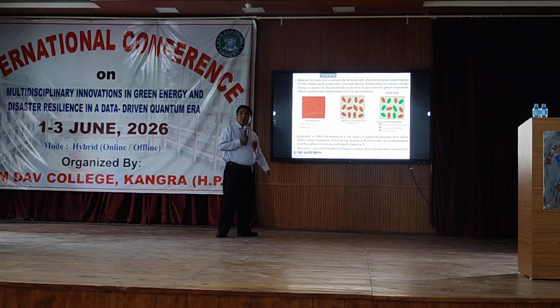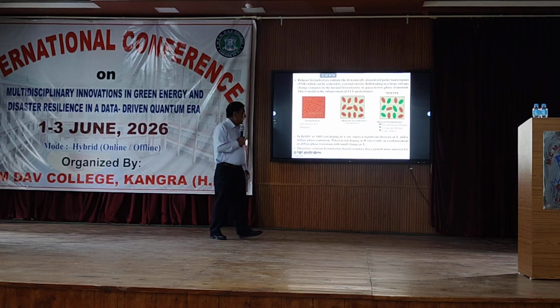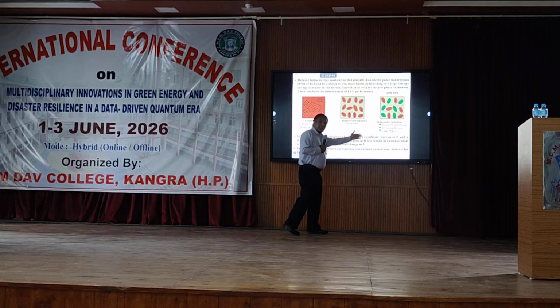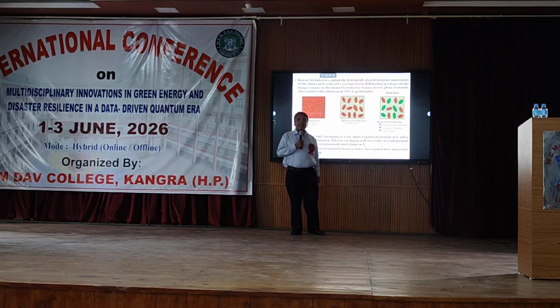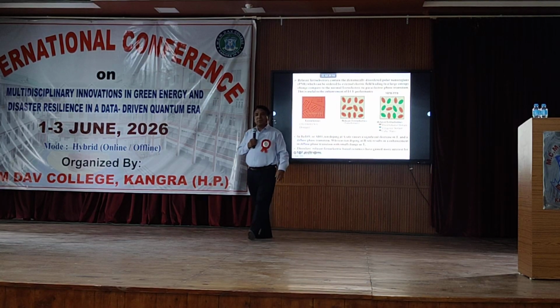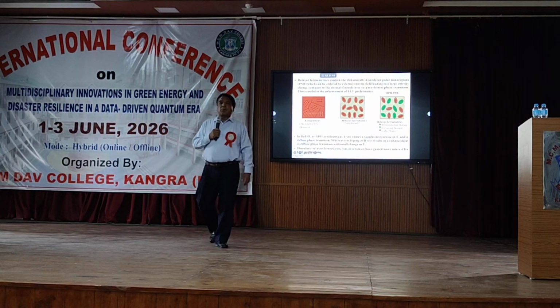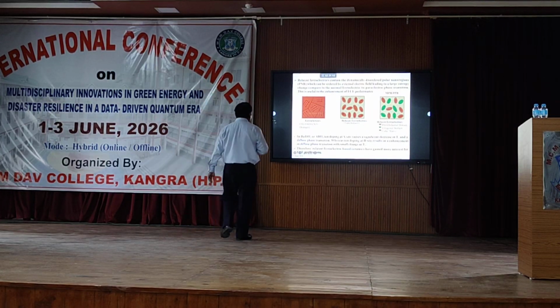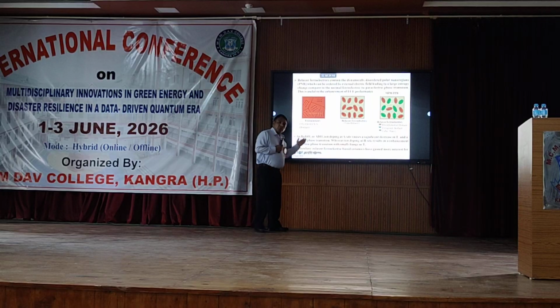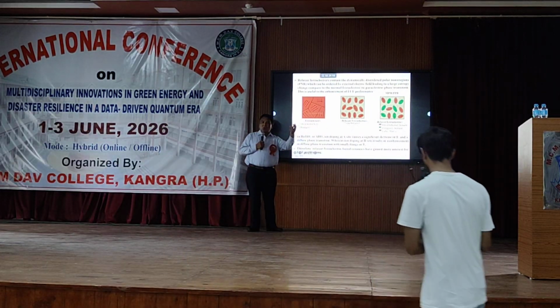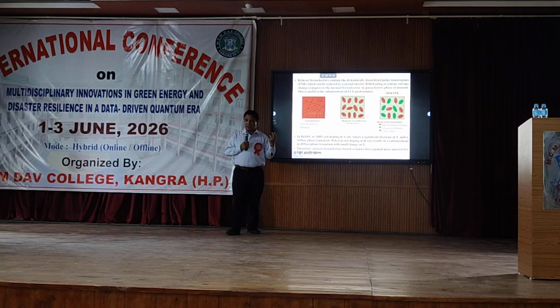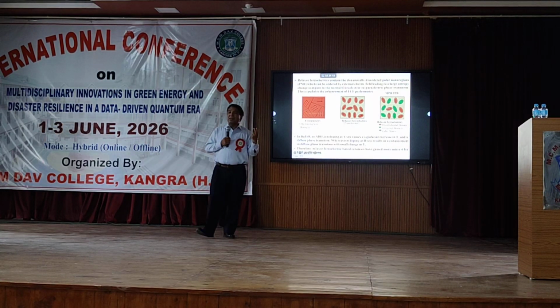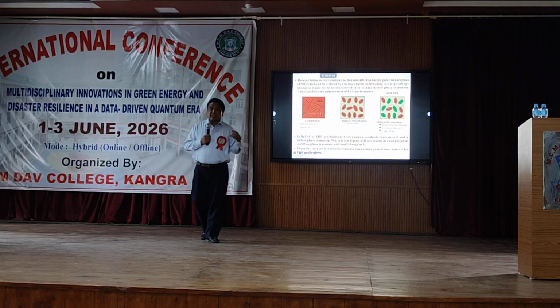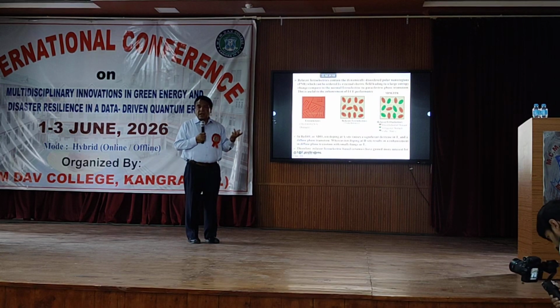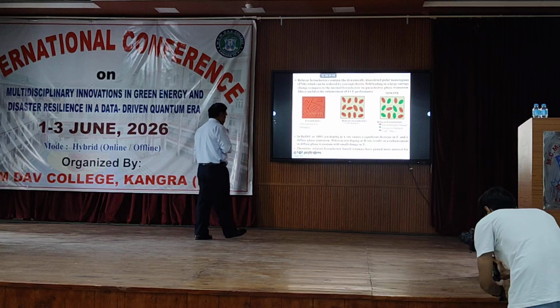And last one, which is morphotropic phase boundary, where there exists rhombohedral, tetragonal, orthorhombic kind of domains within the material, again very useful to enhance the polarization value. So barium titanate has very high Curie temperature, around 130 degrees centigrade. So first objective is to bring down the Curie temperature near the room temperature, because there the sensitivity of polarization on the temperature is large. So one can have high electrocaloric effect near the room temperature.